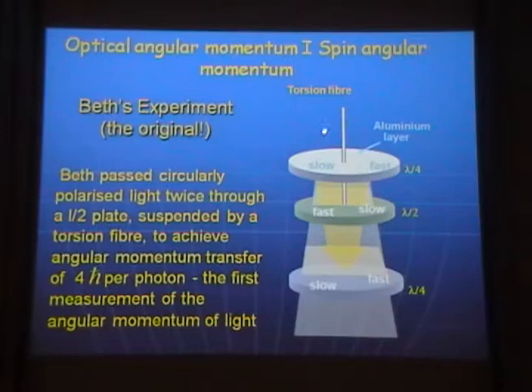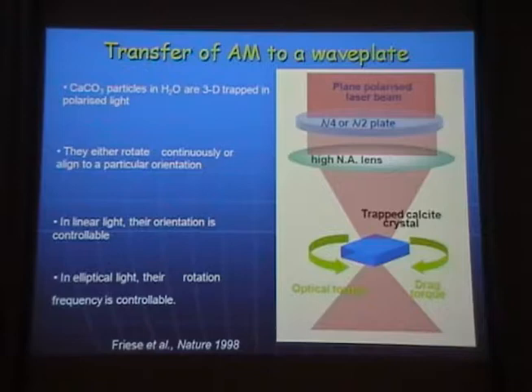So what we want to do, so here we have a lambda over 4 plate, and so we want to find a material which will act as a lambda over 4 plate, put circularly polarized light on it, and put it through a high numerical aperture objective, and see that we can repeat this experiment on a microscale. So, he did it in 1936, and we did it a few years later, so we achieved a transfer of angular momentum of light. Okay, so I have plane polarized light, I put it through either a lambda over 2 or lambda over 4 plate, I have a high numerical aperture, and now I need to have a lambda over 4 plate. So I have to have a material. You know that a lambda over 4 plate is made out of a material which is birefringent.